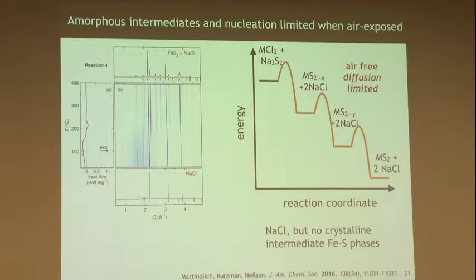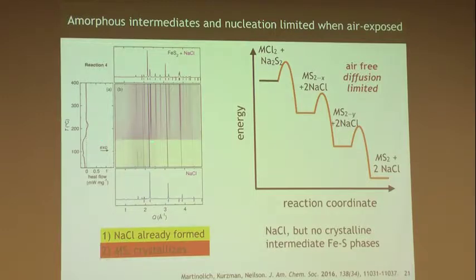No amount of iron or sulfur is visible from powder diffraction. It's in there, but it's not a crystalline phase. So our sodium chloride's already formed, and then after heating to about 150 degrees Celsius, the iron pyrite crystallizes directly. I'll point out that this behavior is identical in nickel and cobalt, but with completely different crystal structures for nickel.